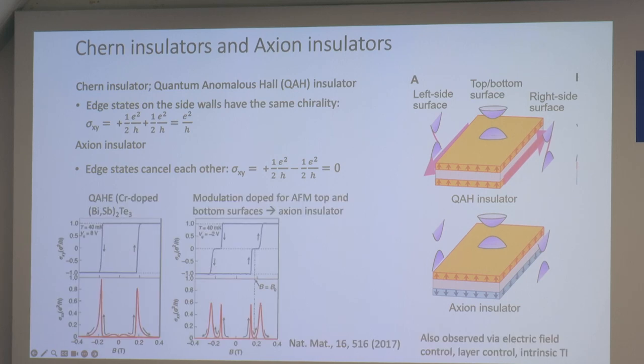And when this is done, in this case, for example, they took chrome doped bismuth selenide, or bismuth telluride in this case, and for the basic chrome doped material you see the quantum anomalous Hall effect very nicely. And then when they modulation dope it, so the top and bottom surfaces have different doping and end up having different magnetic orientations, you see this zero step in the Hall conductance, which is an initial convincing piece of evidence that you have something approaching an axion insulator experimentally. And again, this has been shown many times over since then in different sorts of systems, but this is the sort of data that you expect there.